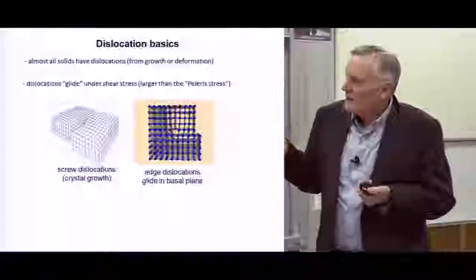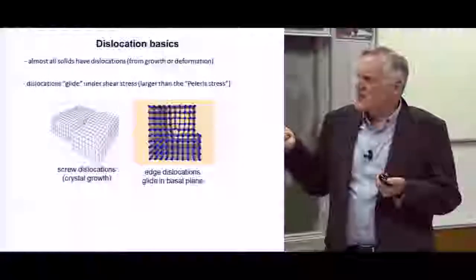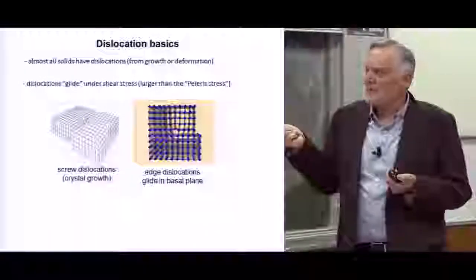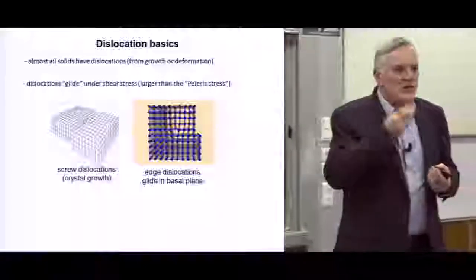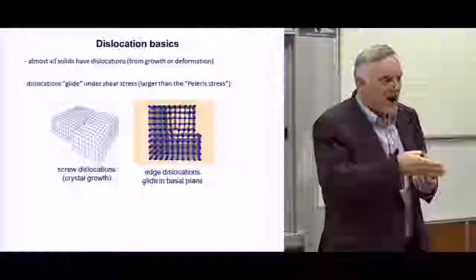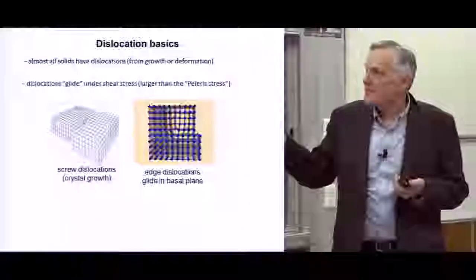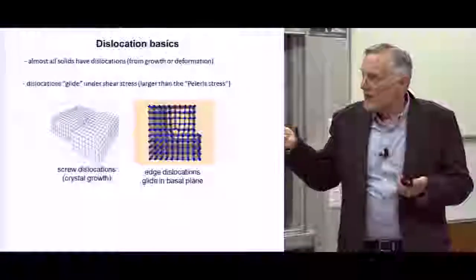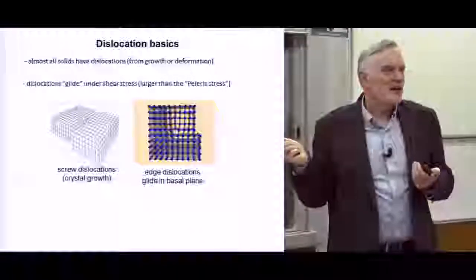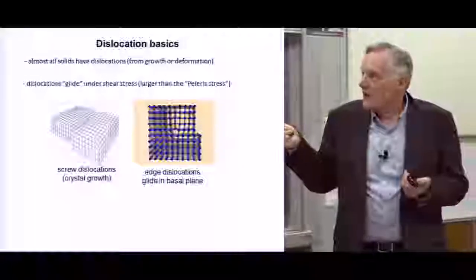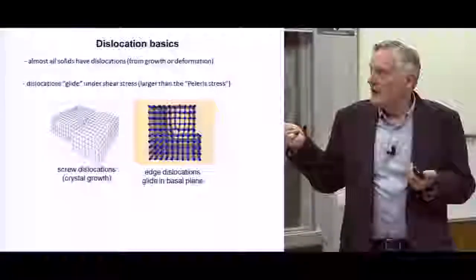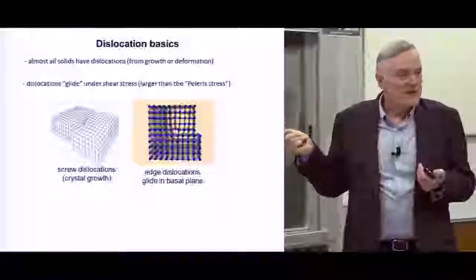So what are they? Well, they're screw and edge. There's two kinds. This one's easier to describe, and it's the one we think is important. If you imagine you take a perfect crystal, you cut halfway through it and slip a half plane of atoms into it from the top, these pink ones, the edge of this is a line going into the board, and that's your edge dislocation. It's a defect. Locally, there's lots of strain. Far away, the crystal is perfect, but you've inserted a half plane.